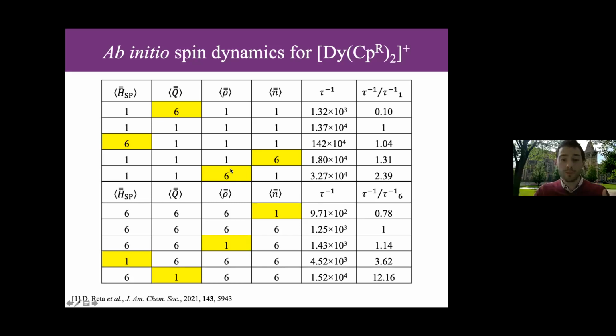And then we could do the reverse. So we can take the matrices just from compound 6, the Layfield compound, and then swap out those parts individually. And what we find again is sort of the reverse, that when we swap out the occupation term here, Q, for compound 1, we get a factor of 10 increase. So this way it got 10 times slower, but then doing it the other way around, so replacing it the other way, you get 10 times faster.